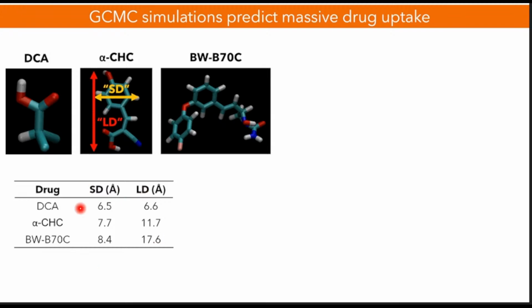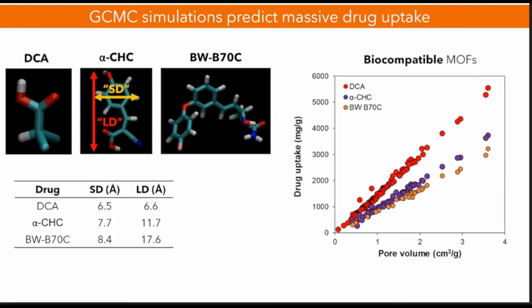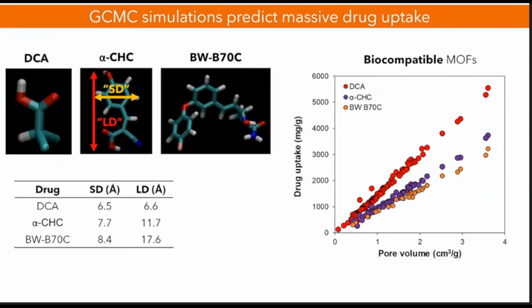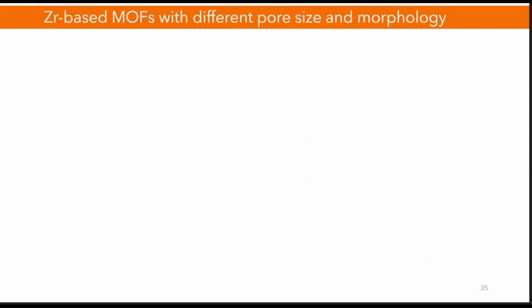So we can have different values for all these different molecules. Basically, when we selected biocompatible metal organic frameworks with zinc, iron, and zirconium metal clusters, we ran these Monte Carlo simulations, and we got these different trends that we have here. This is important because now we can see how molecular simulations can help us identify optimal materials, and we can really go for these structures that we have here. Depending on the drug molecules, we will say we should pay attention to these MOFs or to any other one that we have here. So there is a lot of flexibility in what we can do with the computers.